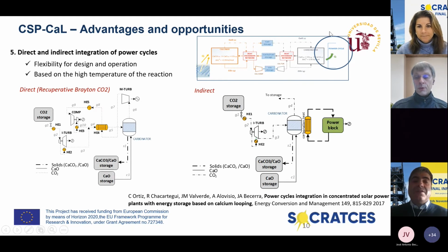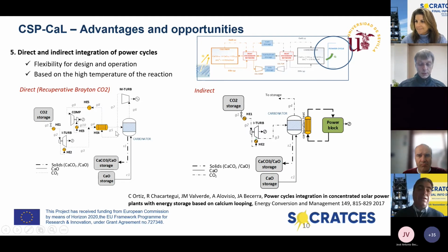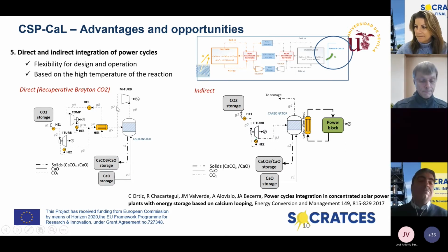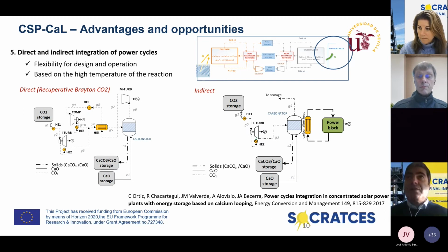Also, considering the direct and indirect integration, we can use this excess CO2 in the carbonator directly as heat transfer fluid, evolving through the turbine in a direct integration, avoiding the use of additional heat exchangers for the power cycle, but with challenges regarding the integration and dealing with the granular media separation. But it also allows the indirect integration, in which heat exchangers are provided between the heat release in the carbonator and the power block. It allows the integration of well-established technologies such as Rankine cycles, also externally fired gas turbines, or, for instance, the supercritical CO2 cycle, still under development.